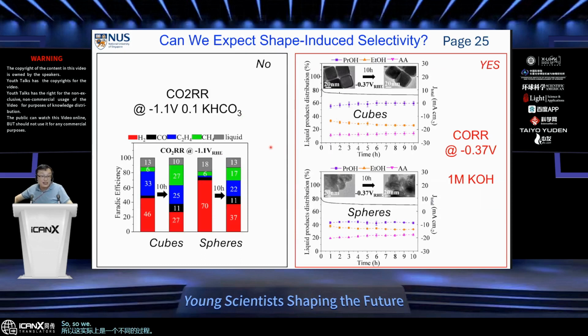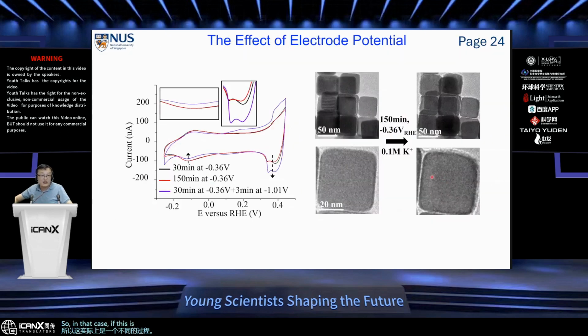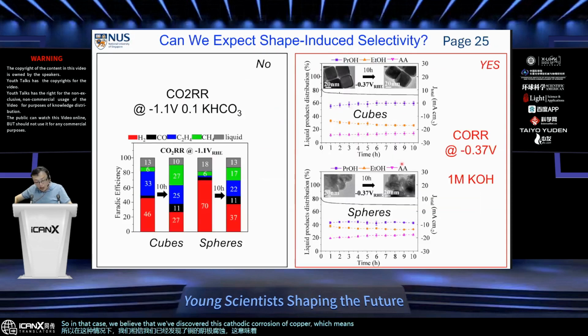So in that case, we believe that we've discovered this cathodic corrosion of copper, which means in your typical CO2 reduction condition, which typically happens at minus 1 volt in the potassium-containing electrolyte, the catalyst surface will always change. That means if you try to create a cube which gives you more 100 surface, or if you compare with a spherical particle which gives you all kinds of different facets, the selectivity advantage that you have in this case to the acetylene in the beginning will not last.